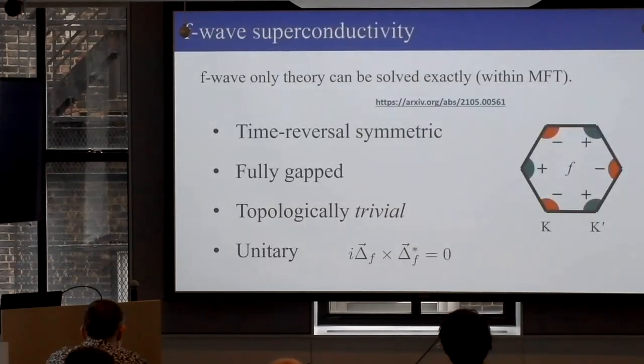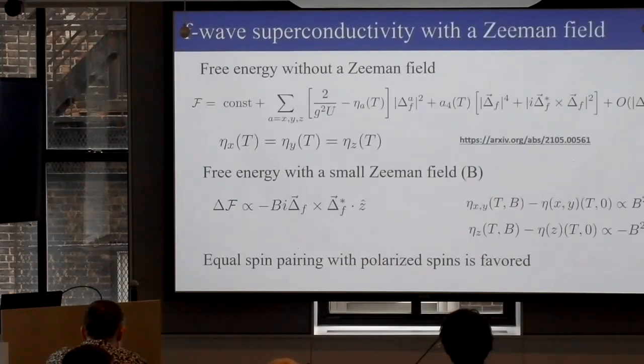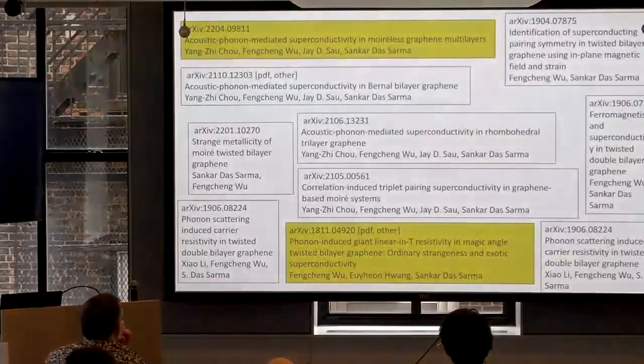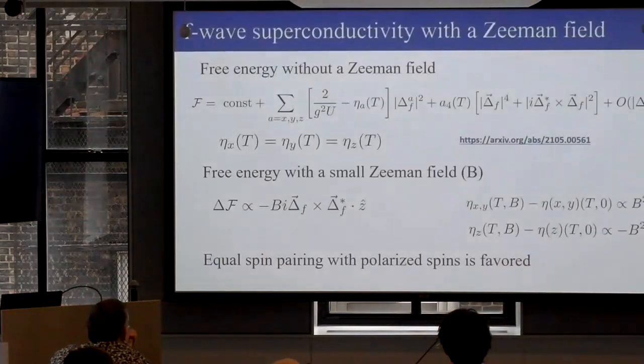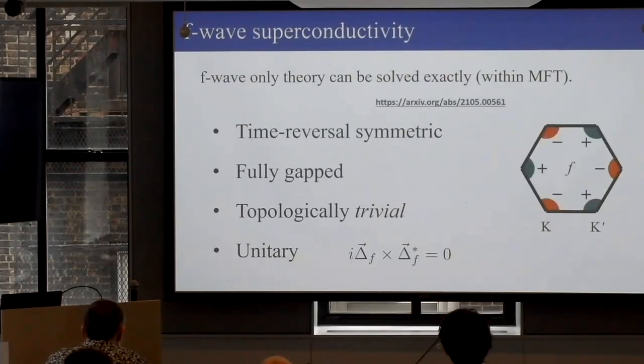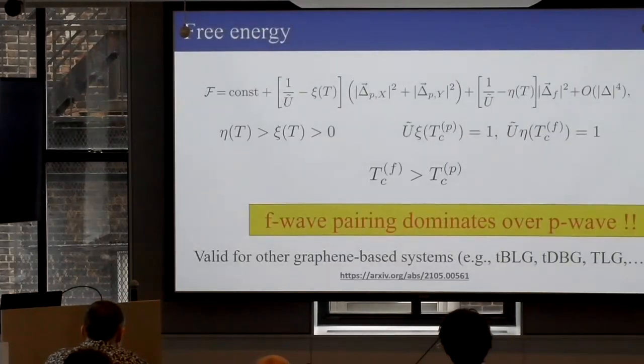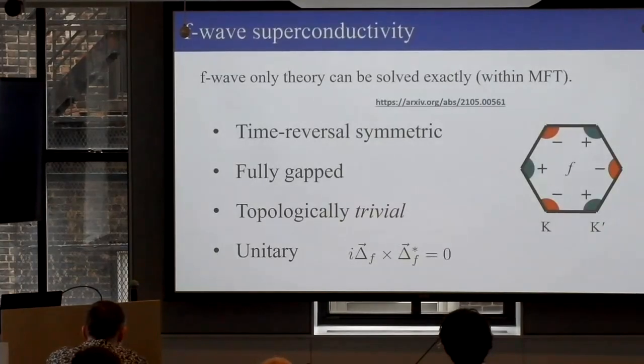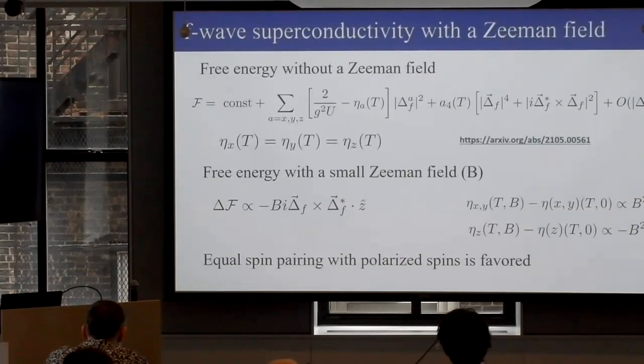And then we can go further forward, and we can solve the problem exactly if we just keep the F wave. Okay, we did that. We can calculate all the free energy and find out how that will change in magnetic field. So we made a lot of predictions, and to my total amazement, this is not an important paper, but this got accepted in PRL because I think the important conclusion is that even for this, you get F wave pairing. And once you say F wave pairing, we can solve the problem exactly. And then we can give some idea about what would happen in the presence of small Zeeman field and what the issue is.